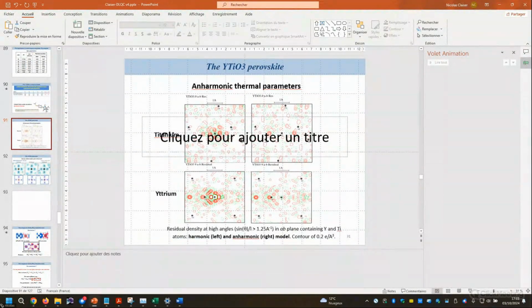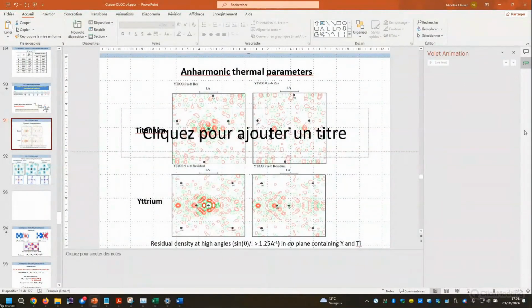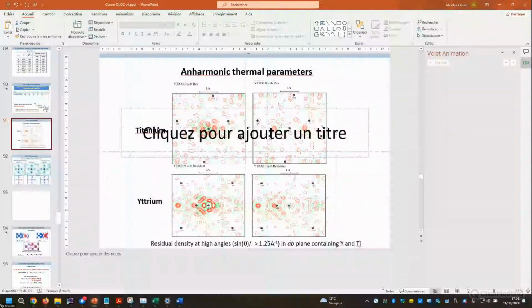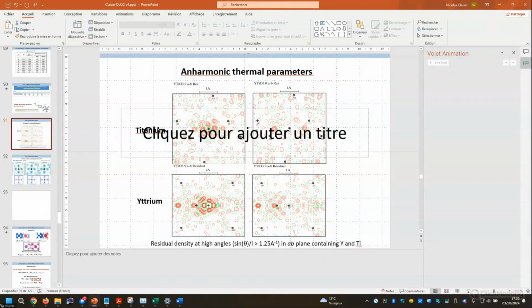In that case, you can see that with a classical treatment of the thermal parameters on the left, you have huge residual maps that are completely improved if you introduce anharmonic thermal parameters. I think one of the difficulties of the joint refinement is that you don't have any recipe. Each sample is different, and I will not be able to tell you that a weighting scheme will work all the time. It could introduce some bias. So you have to check at every stage of the refinement that you are not introducing a bias because you are not taking all the parameters into account.